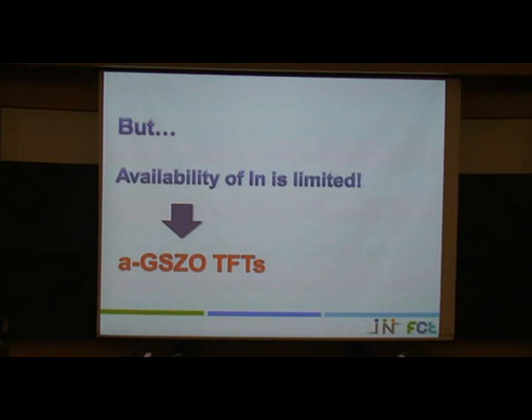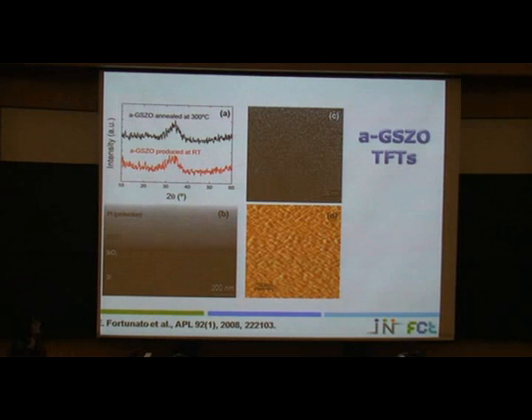We all know that the availability of indium is limited, and we substituted in our system the indium by tin, and the results are good. For example, here the materials are still amorphous. This is the typical diffractogram of a gallium tin zinc oxide film produced at room temperature and annealed at 300 degrees. The structure is amorphous. This is a SEM cross section, and this is an AFM topography.